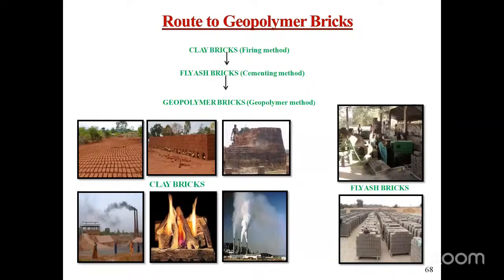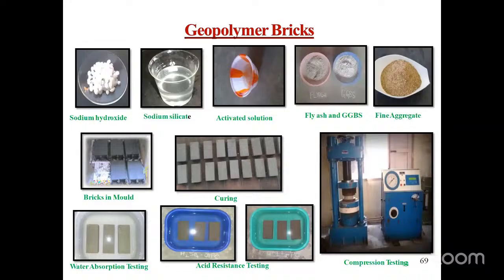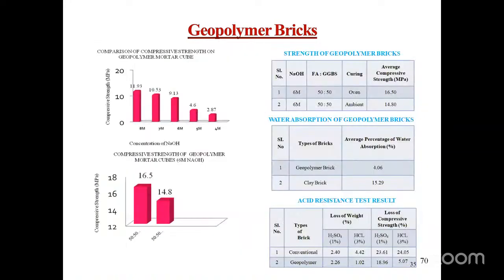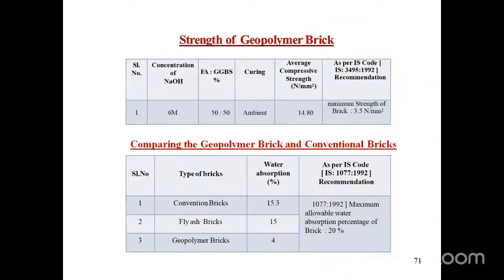Similarly, we made geopolymer bricks. So in geopolymer bricks, clay is completely eliminated. In fly ash bricks, people are using cement. Here, cement is also completely eliminated. Only fly ash and GGBS and fine aggregate, that is sand, mixed with alkaline solution, you can get these geopolymer bricks. The comparison was also made, and we proved geopolymer technology is very well adopted in case of concrete as well as bricks.